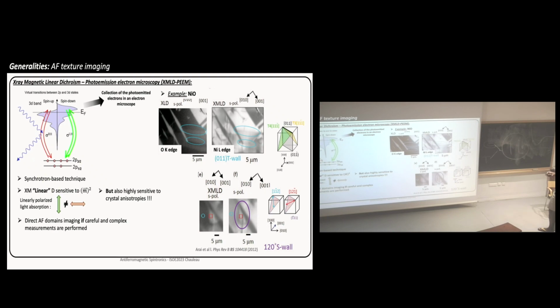And it has been nicely done anyway, for example, if you take this paper. Here it's NiO samples, and here you have two images. Either you tune the wavelength at the oxygen edge, so you should not see any magnetism, you will see only some crystal anisotropy. And if you tune it to the nickel edge, then you can have both crystal anisotropy plus, to some extent, magnetism. But if you do a careful analysis, and this one is quite complicated because you need to rotate the sample in different directions, you need to use several angles for the incident light, then you can identify some domains.